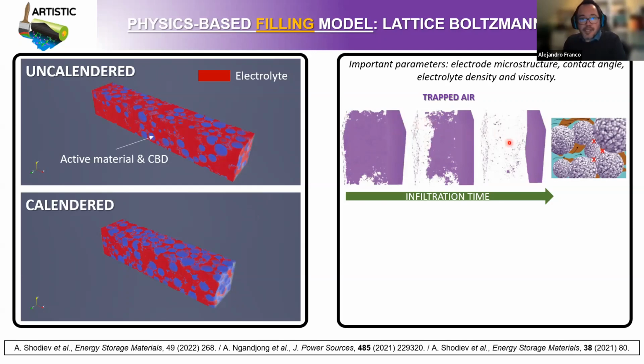Here you see results from this lattice-Boltzmann method simulation. This is the predicted spatial distribution of trapped air in the electrode porosity. You see here a lot of air bubbles which remain inside the electrode volume after the electrolyte infiltration. And this is, of course, problematic because if you have air instead of liquid electrolyte, then your active material is not going to be fully active upon lithiation or delithiation, which is an electrochemical process. You need lithium ions to arrive at the surface of the active material. If you have air, the lithium ion is not going to arrive at the active material, right? And then you will lose performance for your lithium-ion battery cell. You will lose energy density, you will lose power density, right?